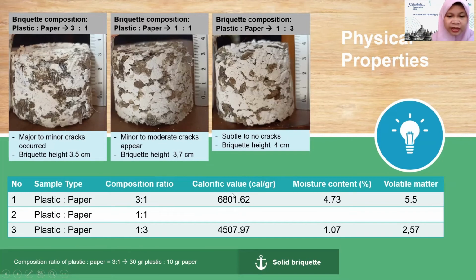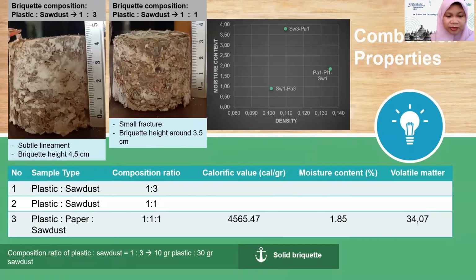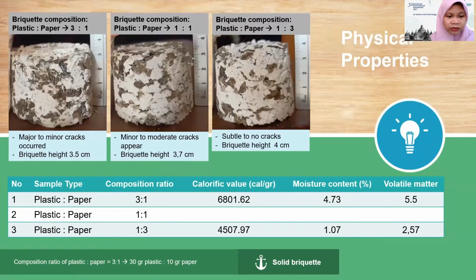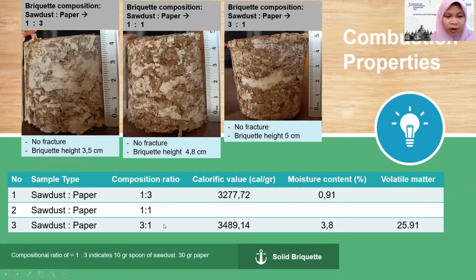As you can see, this one has a calorific value of about 6,800 something, while the lowest one is found in the calorific value of the mixture of sawdust and paper with the ratio of 1/3. So this is the lowest calorific value. It suggests that plastic presents as a combustible material better than sawdust bonded with paper.